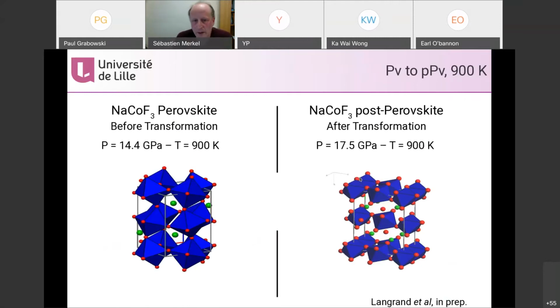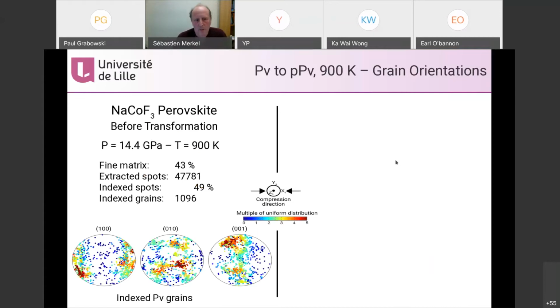What I'm going to show now are the statistics of grain orientations that we measure in perovskite before the transformation, and then in post-perovskite after the transformation, as we increase pressure from 14 GPa to 17 GPa. When we look at perovskite, we were able to index 1,000 to 1,100 grains. What is plotted below are the projections of the grain orientations, with the diamond cell direction on the side here. If you don't know how to read pole figures, it's okay. What matters is that each point on this figure is a grain, and where it is located on the figure tells you about the grain orientation. And so we are following the orientation of 1,000 grains inside the sample.